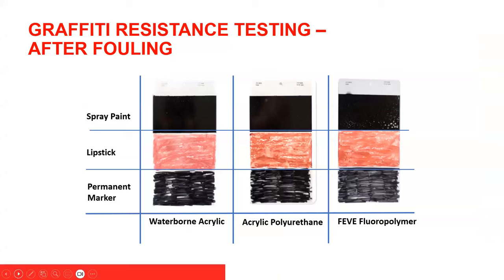And so one thing that we do as a manufacturer is we'll test our top coats to see how they withstand the cleaning that's necessary if something were to get tagged with graffiti. In this case, what you're looking at, the three columns from left to right are panels, or Leneta cards, as we call them, with a waterborne acrylic, an acrylic polyurethane, which is kind of the standard high-performance top coat chosen for many structures, and then a fluoropolymer on the right.